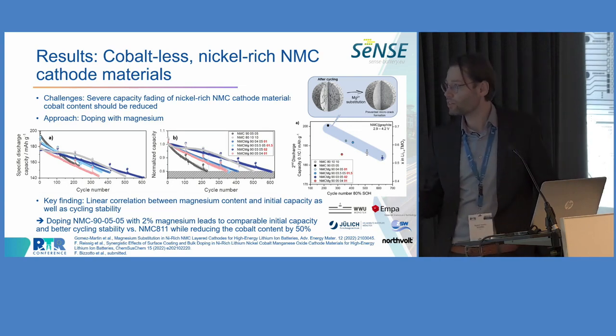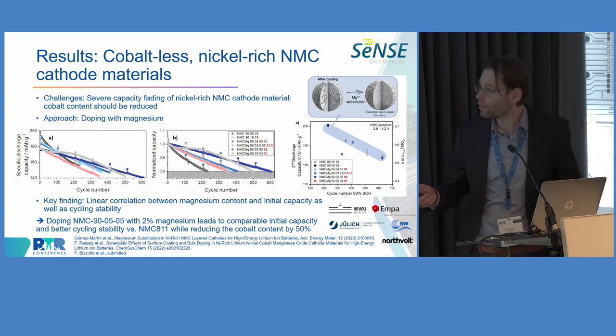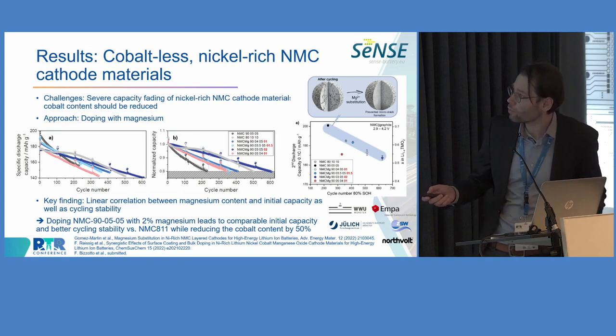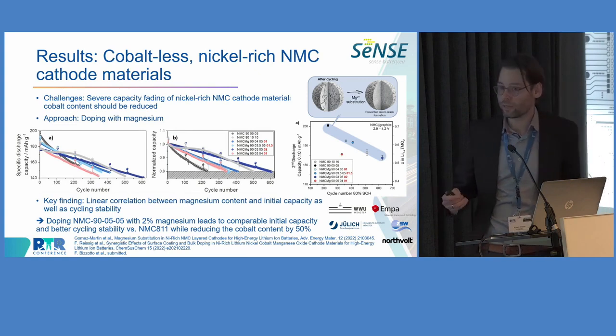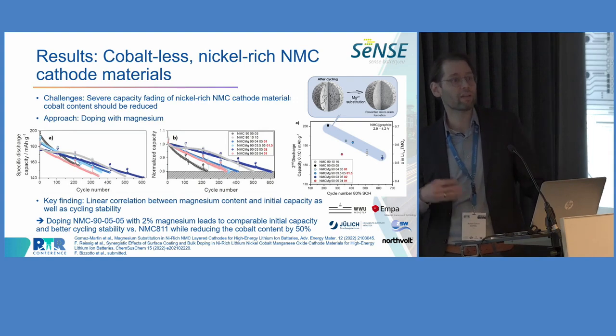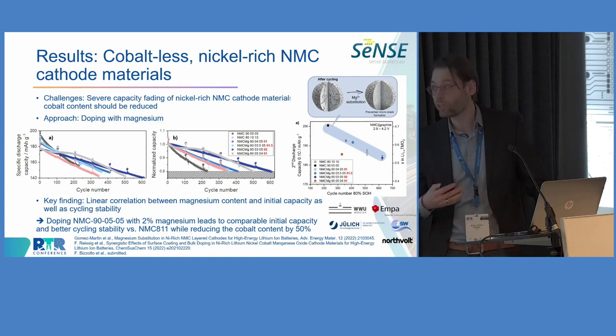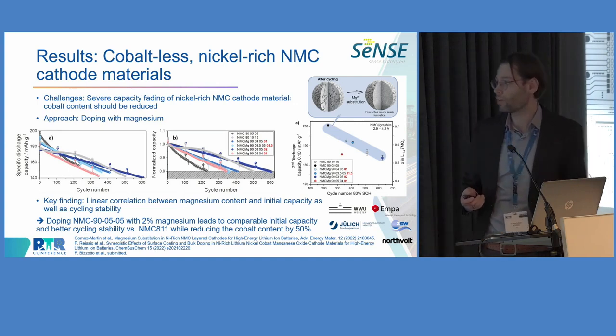And here in this example, we went for NMC 955, so we reduced the cobalt content by 50%. And as you can see here, if we compare here in gray NMC 811 with NMC 955, this really comes at a quite significant penalty in terms of cycling stability. So we have been exploring different approaches to improve the cycling stability, including dopings and coatings, and also working on the electrolyte.